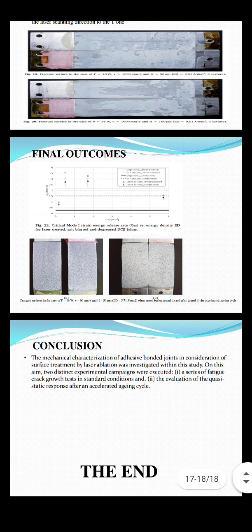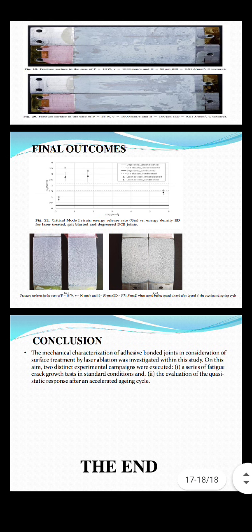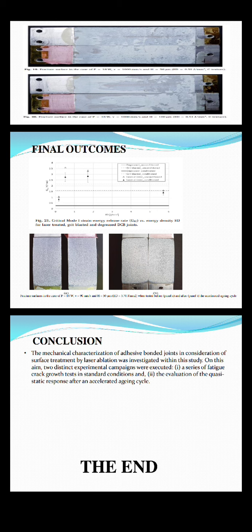Coming back to the conclusion point, the mechanical characterization of the adhesive bonded joints, considering the surface treatment of laser ablation, was investigated in this study. And to this aim, two distinct experimental campaigns were executed. First was the series of fatigue crack growth tests in standard conditions, and second the evaluation of the quasi-static test after the accelerated aging cycle. Okay, thank you. This will end my seminar regarding this topic. Thank you.